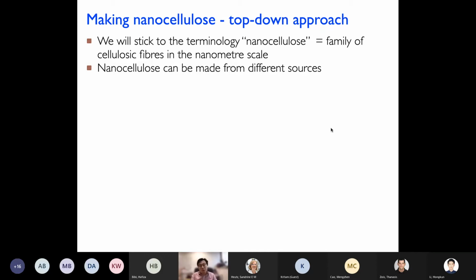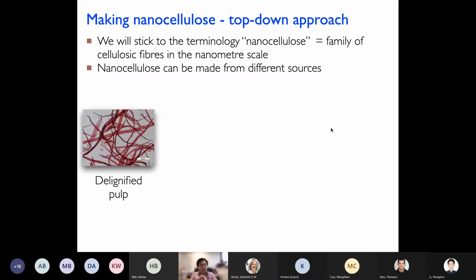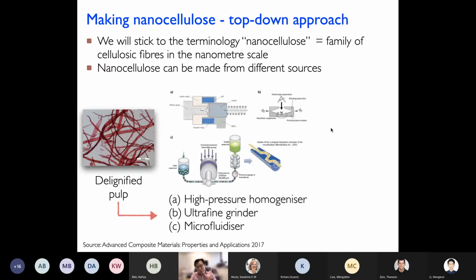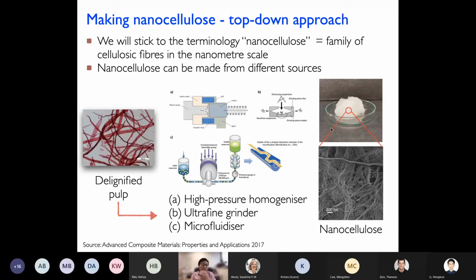And going to the source of nanocellulose, you can actually obtain nanocellulose from different sources. So you can start from wood, which you then convert to pulp. You pass it through, you refine them through high pressure homogenizers, ultra fine grinders, or microfluidizers. And you get what we call a grade of nanocellulose. So on the bottom right-hand side corner here, that essentially is the nanocellulose themselves that you're looking at. So the scale bar is 300 nanometers, and the individual nanocellulose fibers there are 5, 10, 20 nanometers or so.